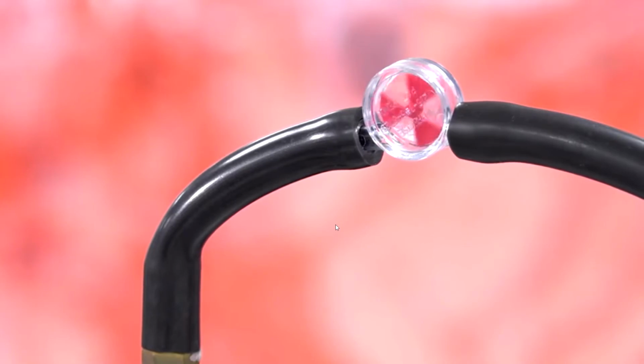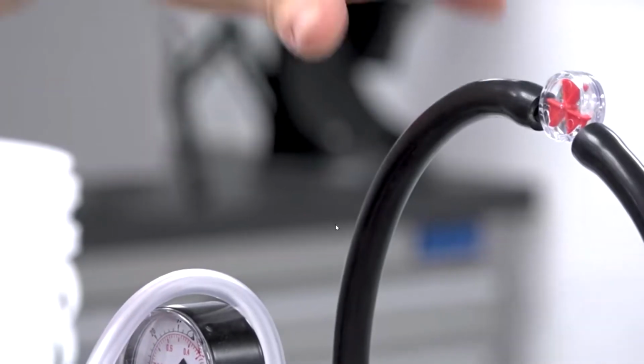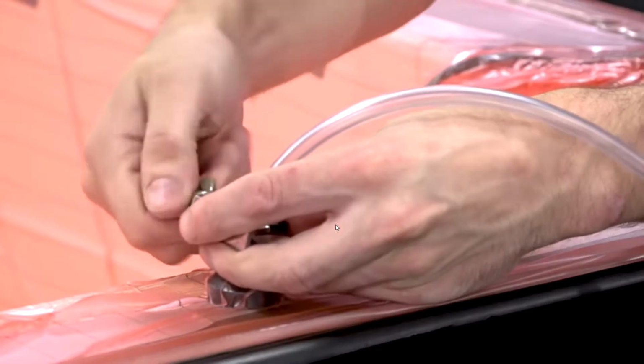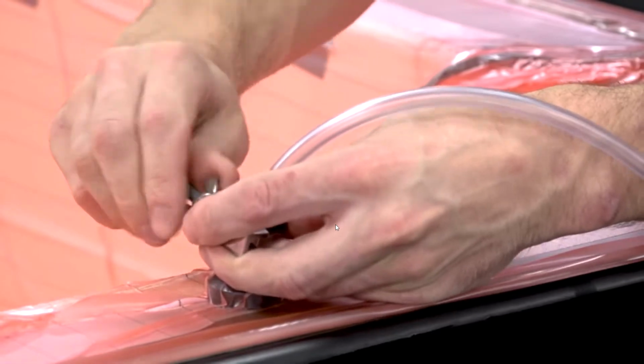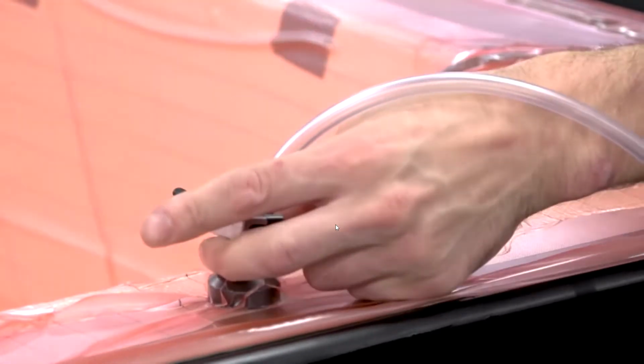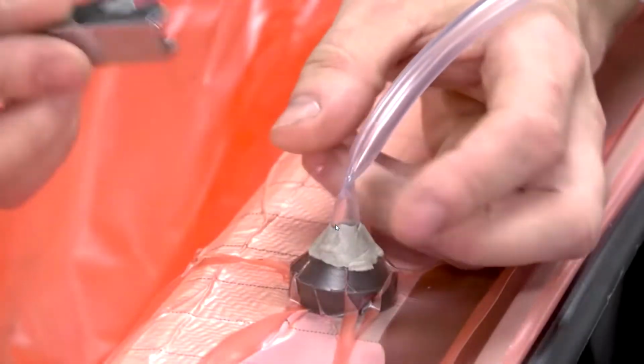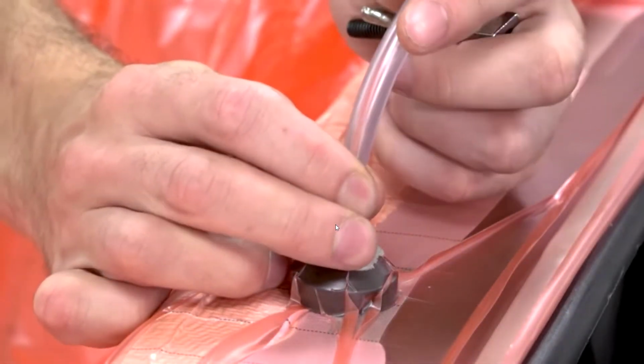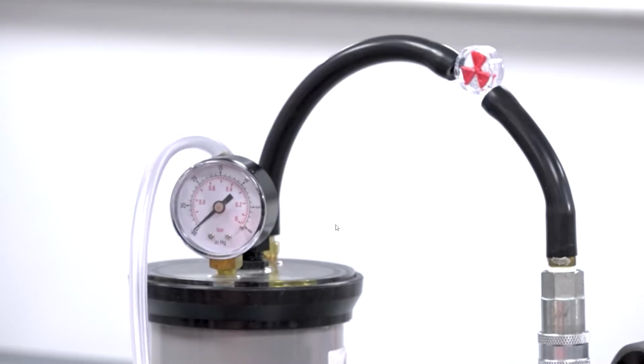A leak flow indicator positioned between the catch pot and the pump will indicate when the vacuum is pulled, as it will stop spinning. Clamping the vacuum line and leaving it for a period of up to 10 minutes will show if any air has been drawn into the vacuum bag. On release of the clamp, any potential air that has got into the vacuum bag will surge through and indicate on the pressure gauge.